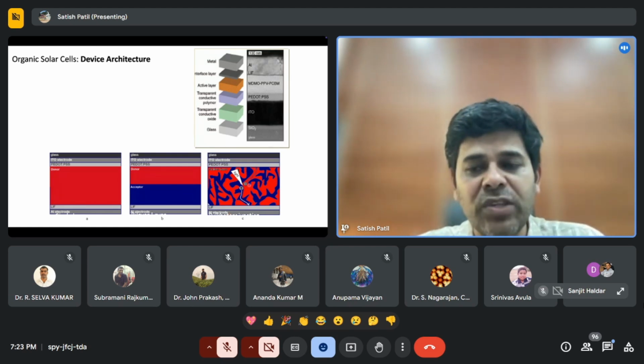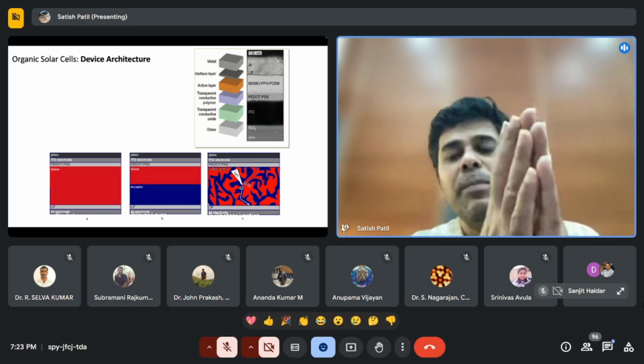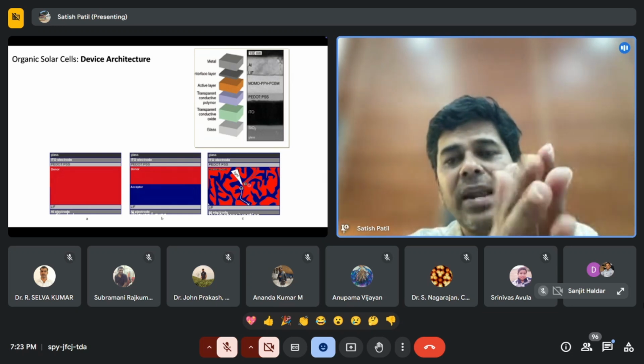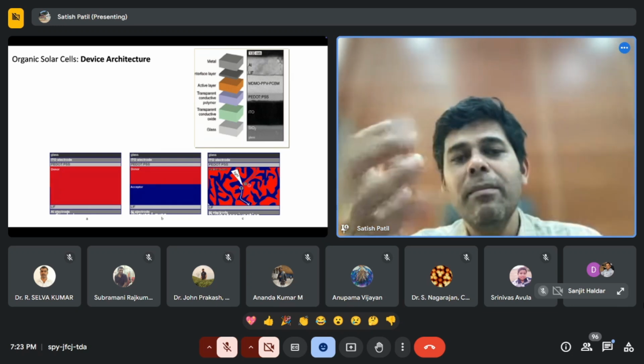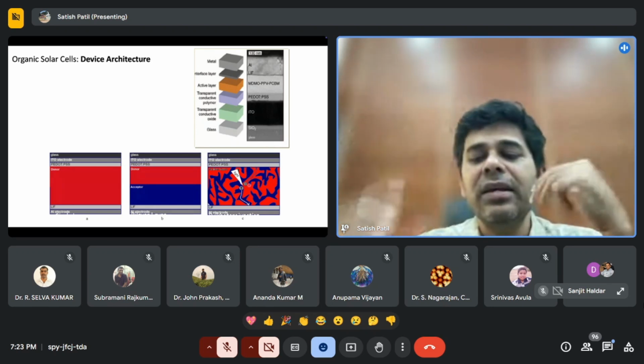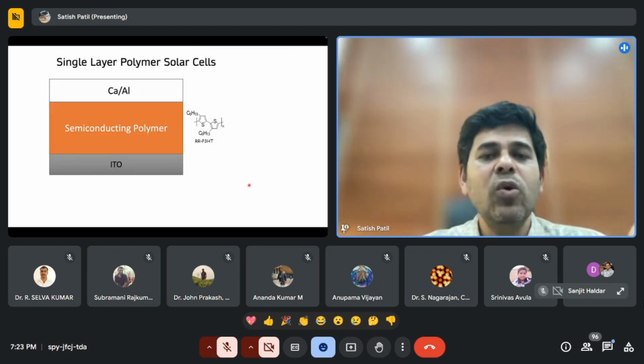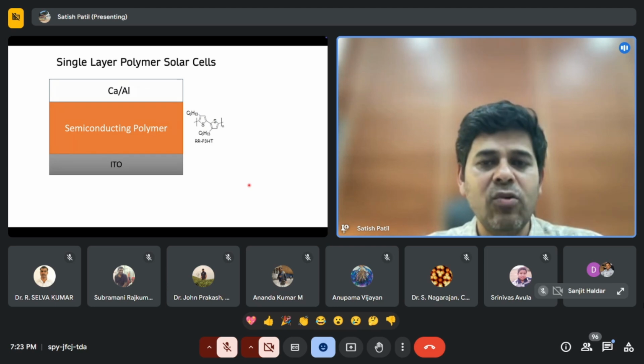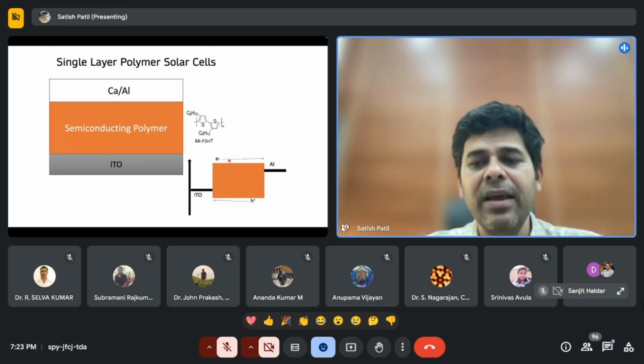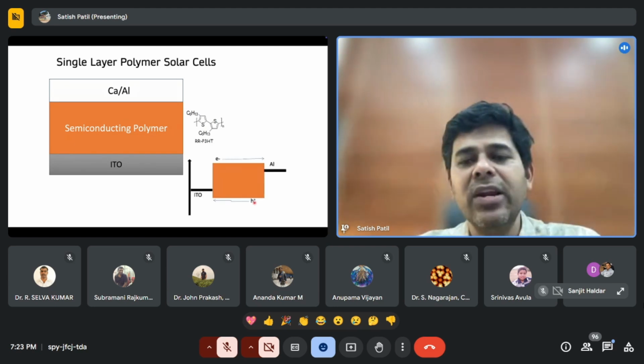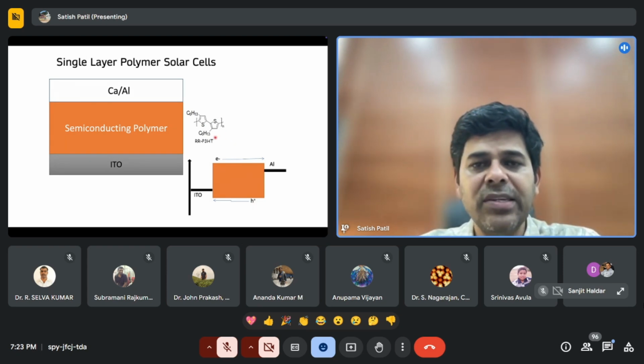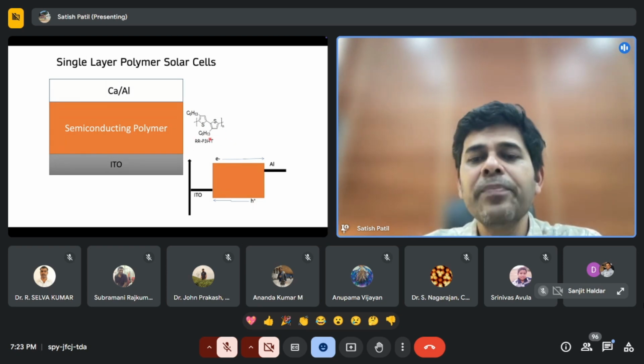People mix these two semiconductors together. They use a P-type conjugated polymer and an N-type layer like PCBM, mix them together, and they get high efficiency. So why don't they work as a single layer? Single layer does not work. For example, in a single layer they recombine rather than separating and holding an electron. Like if you use a P3HT kind of material, then they don't work.